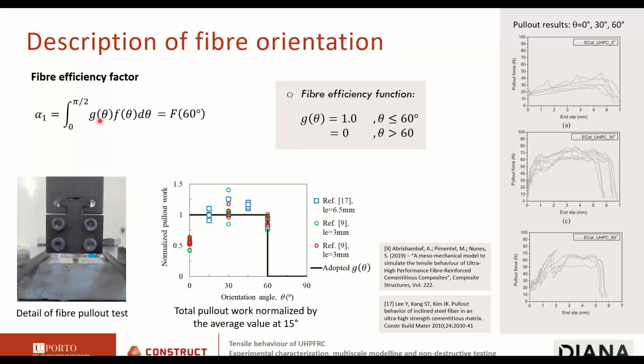So is this reasonable? Well, you see here some results of single fiber pull-out tests that we did here at the lab. Here you have a picture showing it. What do we see? We see that even fibers inclined at 60 degrees can hold very large values of pull-out force, okay? But what we should understand is that these forces develop for slip values that become increasingly large as the fiber angle increases.